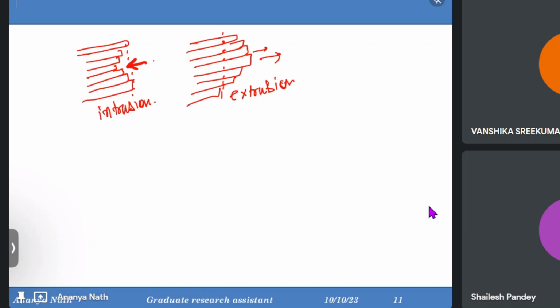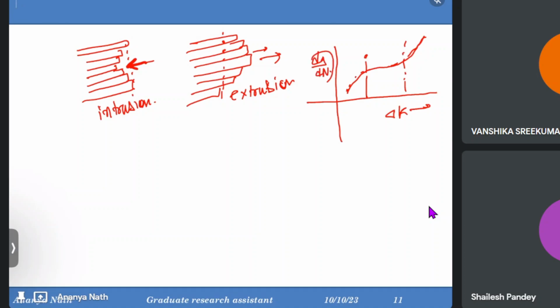So the crack growth also has three different stages, 1, 2, and 3. So the graph looks like this. So there is one stage, second stage, and the third stage. So this is the crack. This is the stress intensity factor, which is again very important in case of fatigue and fracture. And this is the, what is it? Someone tell me. Actually, this is crack growth rate. Yes, crack growth rate. So a is the crack length, and N is the number of reversals, you can say. So with the number of reversals, how much the crack is propagating or growing, that is known as the crack growth.